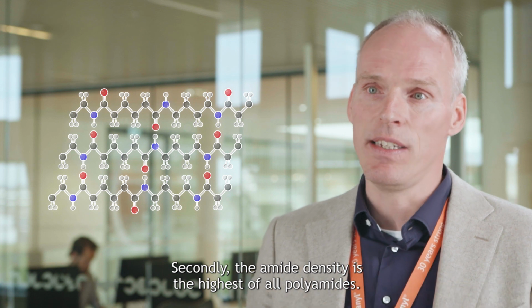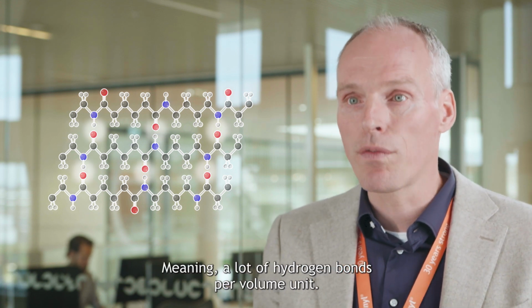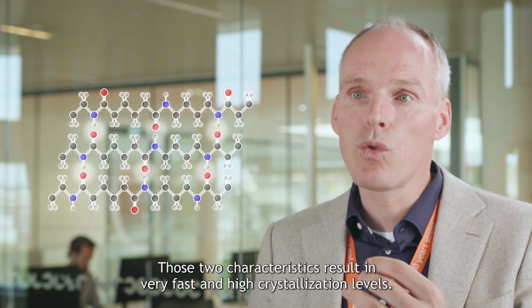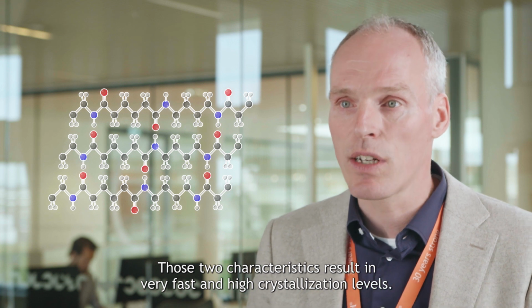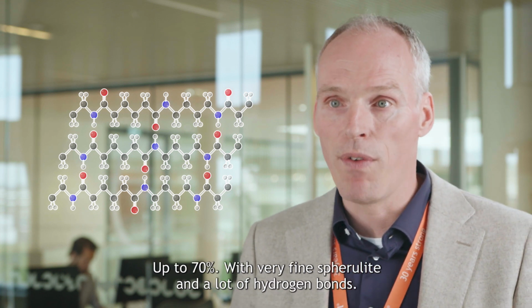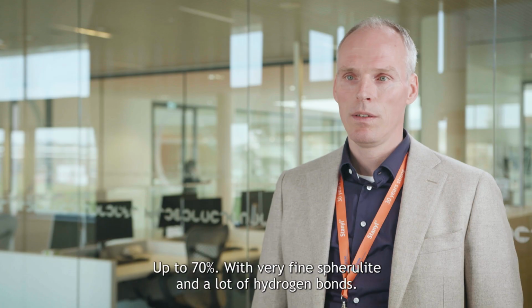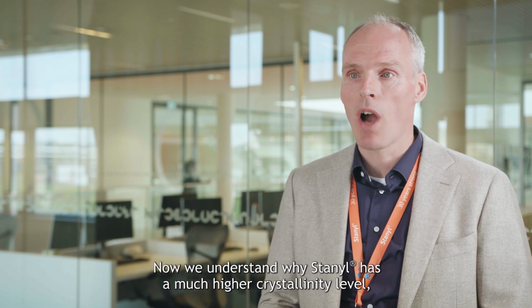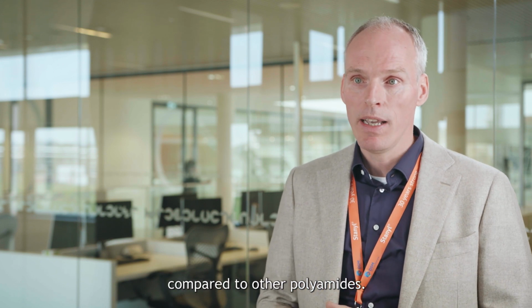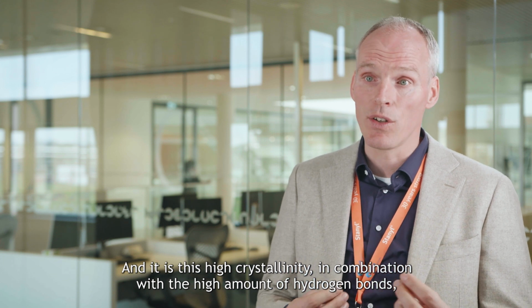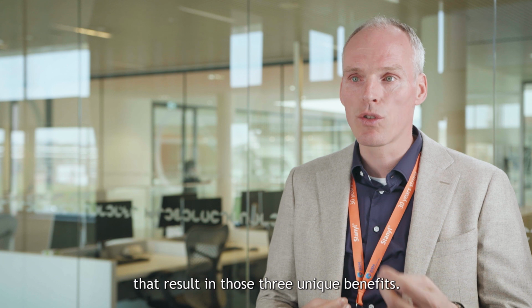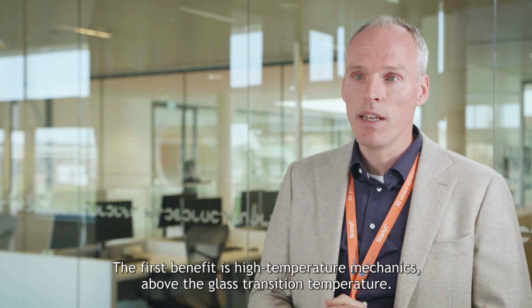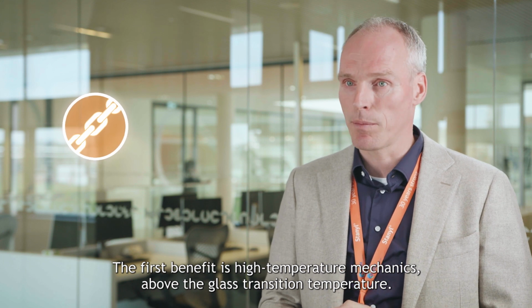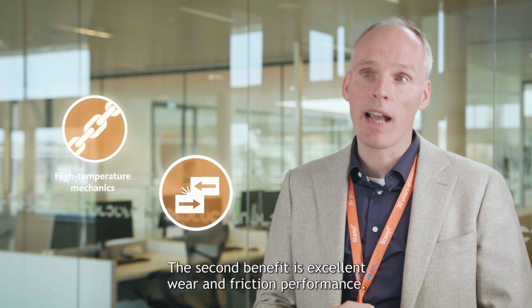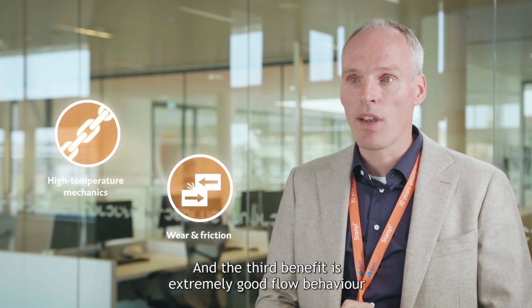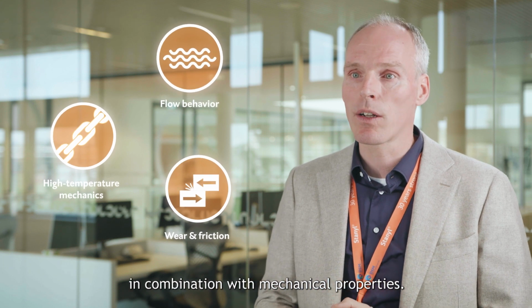Secondly, the amide density is the highest of all polyamides, meaning a lot of hydrogen bonds per volume unit. Those two characteristics result in very fast and high crystallization levels up to 70%, with very fine spherulites and a lot of hydrogen bonds. Now we understand why Stanyl has a much higher crystallinity level compared to other polyamides. And it is this high crystallinity in combination with the high amount of hydrogen bonds that result in those three unique benefits. The first benefit is high temperature mechanics above the glass transition temperature. The second benefit is excellent wear and friction performance. And the third benefit is extremely good flow behavior in combination with mechanical properties.